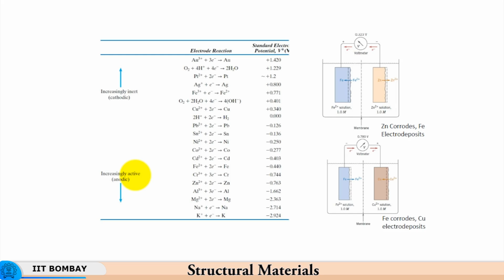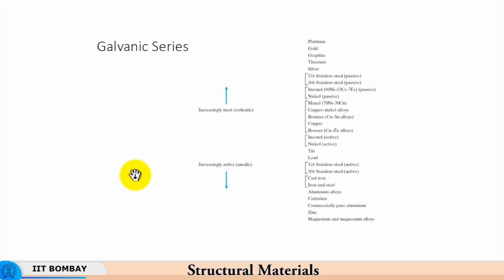So, let us say tool steels for example have a lot of alloy content, and because of this alloy content you have lots of phases in tool steel which might be anodic with respect to the other phases. So, what happens there is you will have a galvanic cell set up, and a tool left in the air and in the presence of humidity will rust quite fast. So, many times tool steels are also seen to corrode quite rapidly. So, the harder the material, the greater the lattice distortion, the greater the state of energy of the crystal lattice, and the more efficient or more severe is the corrosive attack. So, that is what we find in our usual experience.